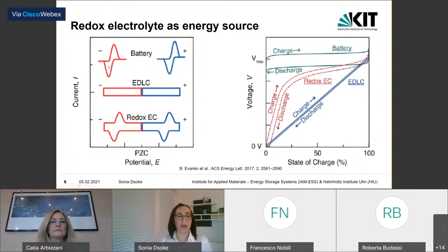So in a battery, normally you can observe in a cyclic voltammetry well-defined redox peaks, and you will observe a plateau in the galvanostatic charge and discharge profile, while in a DLC, you observe only double layer current. So you will not observe Faradaic peaks, and this is also translated in a sloped curve in the galvanostatic charge and discharge. And in the case of a hybrid system, you have a mixture of the two components. So we have a double layer with superimposed redox peaks, and the galvanostatic profile will be in between the two systems, battery and the double layer capacitor.